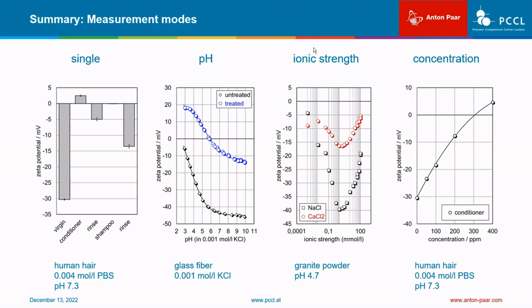If we exchange some electrolyte by a more complex solute, such as a surfactant, a polyelectrolyte, or proteins, we may record a kind of adsorption isotherm by monitoring the Zeta potential with increasing concentration of this solute in the aqueous solution.